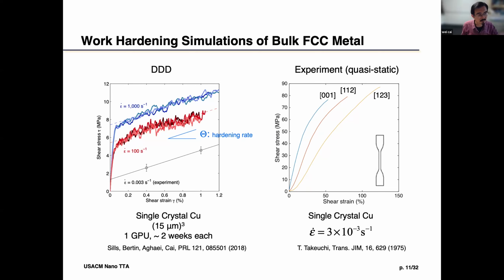But the flow stress itself does not, and that is probably because the strain rate we have is too high, and then you sort of have to pay an overhead to get the dislocation moving at a much faster speed. So if you make the assumption that maybe the high strain rate really just adds an overall flow stress to everybody, then maybe there's a good reason why the strain hardening rate that we get here is actually quite consistent with the experimental strain hardening rate. So I say, in some sense, a qualitative or semi-quantitative comparison, if you just compare the strain hardening rate, I think it was good, or that's what we could do at the time.